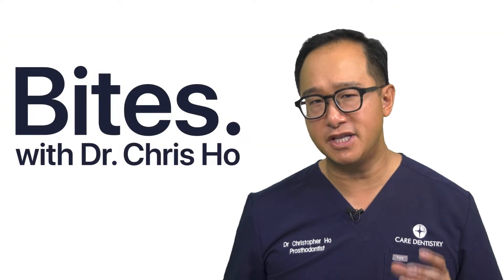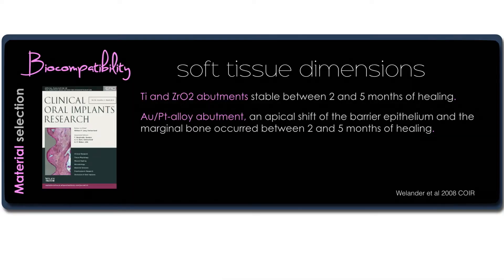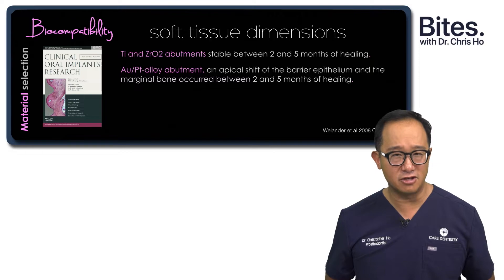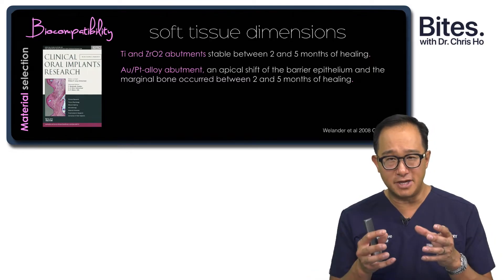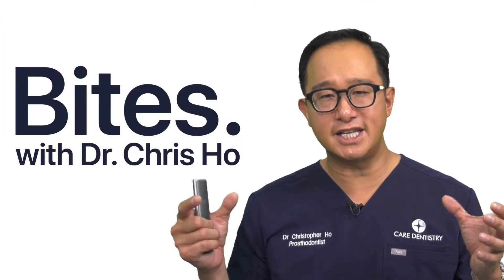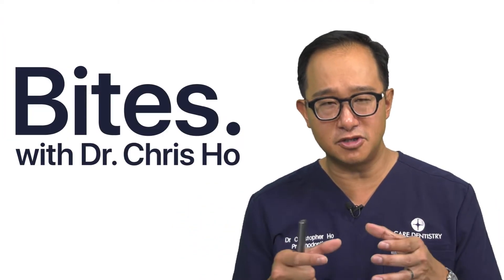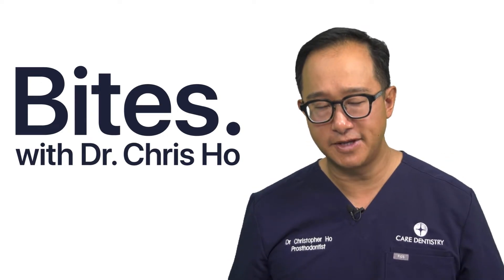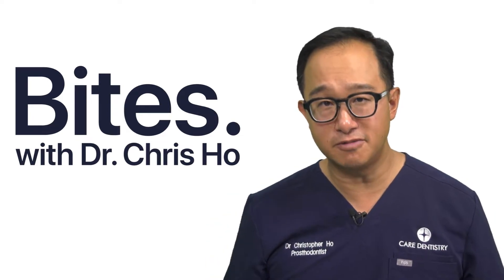But there are some other benefits apart from just aesthetics, and one of those is biocompatibility. We know that with titanium and zirconia abutments, we have stable soft tissue attachment — we are able to attain connective tissue attachment to these abutments. Whereas if you use gold or platinum alloy abutments, or even veneering porcelain around your abutments, you actually get an apical shift of the barrier epithelium, so you don't get attachment to these materials. With titanium and zirconia, you get good soft tissue attachment, which means a very good seal around your abutments.